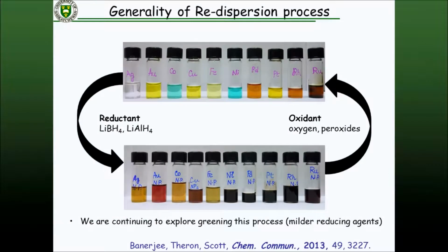So we wanted to continue to play with this redispersion and see how general it was. So I challenged the students in my lab to go through all the possible catalytic transition metals and see how many of them you can redisperse in the ionic liquids. And the answer is pretty much all of them. The only system we have a little bit of trouble with is iron. X-ray absorption studies show that the iron nanoparticles actually aren't pure iron nanoparticles, they're a little bit oxidized. You have trouble completely reducing the iron. But nevertheless, in all the other systems, it's very easy to make particles with any kind of reducing agent. For some of the 3D transition metals, you need stronger reducing agents, such as lithium aluminum hydride.